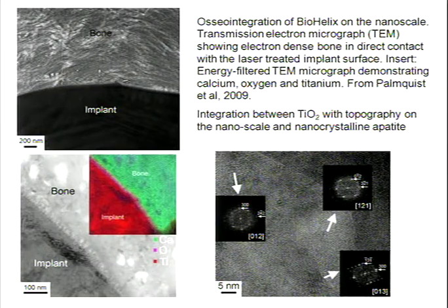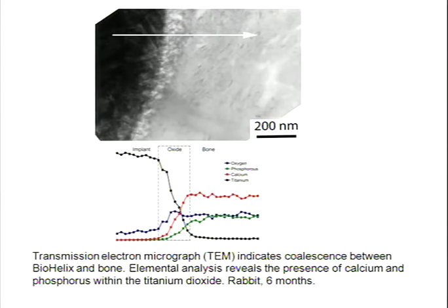But here comes the thing. This interface between living hydroxyapatite and titanium oxide is dependent on the interfacing between small nano-sized nanoapatite crystals and the surface oxide. And this interface we actually don't see with very many implants yet. So we know that nanoscale surface features induce such an interface.